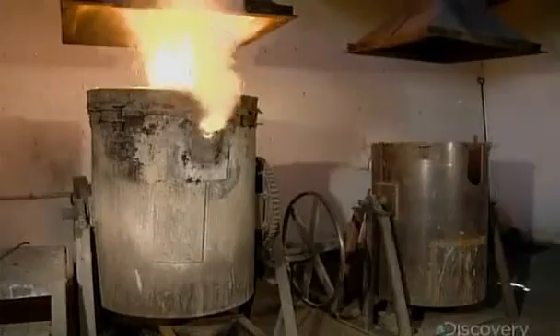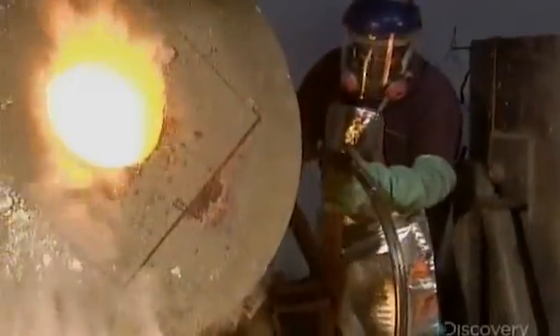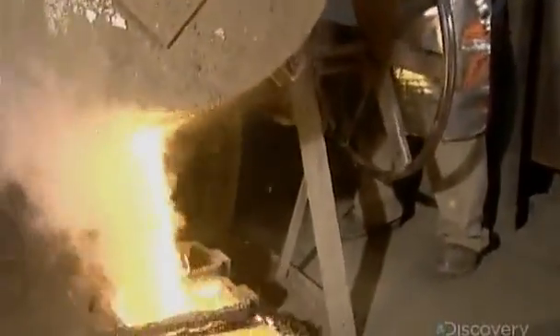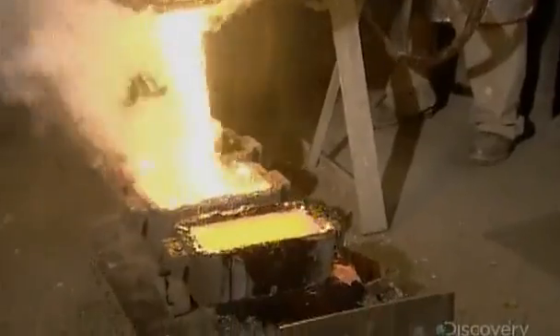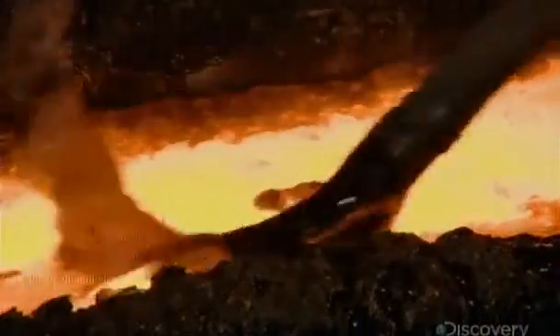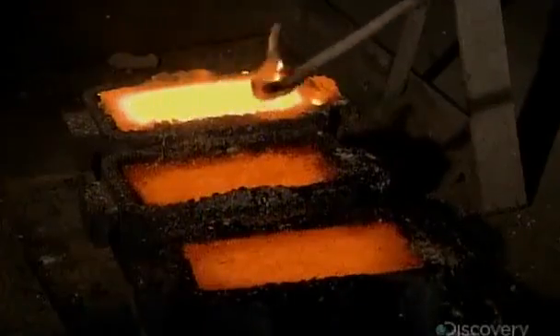Back at the mill, workers put the now dried silver precipitate into an oven, along with chemicals which prevent silver from burning off. Approximately 4 hours later, the silver and waste have separated and melted. Workers pour them into bar-shaped molds. The silver, being heavier, settles at the bottom. Workers skim off the waste floating on top.